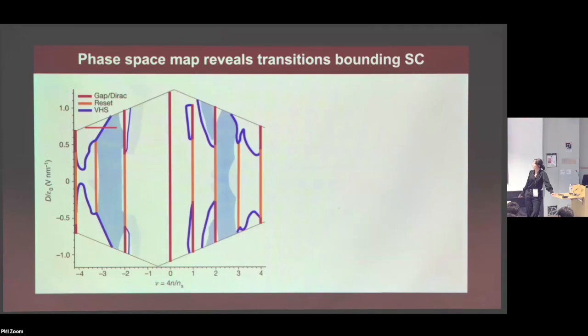The first thing that you can realize is that these superconducting regions are exactly bounded by both the reset and Van Hove singularity features, where something is going on for your Fermi surface. So that already tells you that superconductivity must be related to some sort of symmetry breaking that's going on in the system in these particular regions.